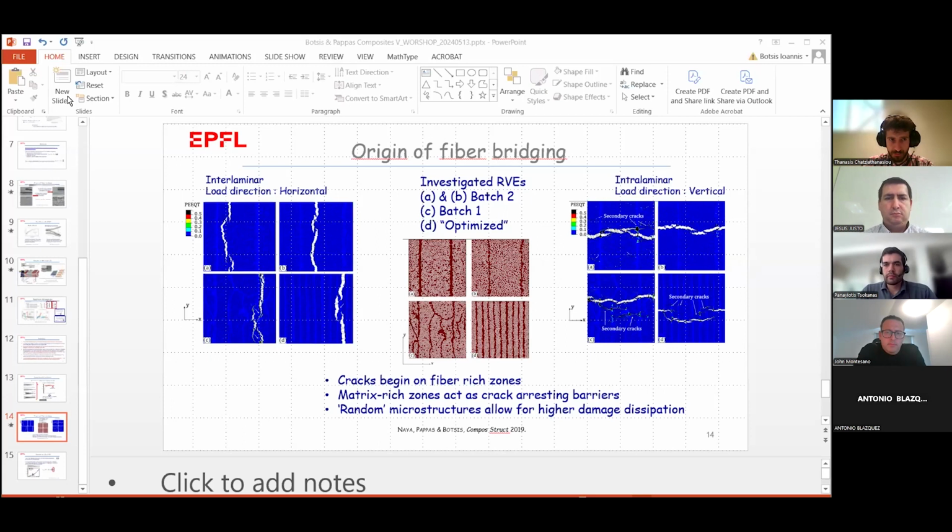At the very beginning, we are talking about delamination involving 10 fibers, 15 fibers, which is nothing. Now, when you obtain bigger delamination values, you notice it in the microstructure. If you are in mode one, the separation between fiber and matrix is like this. If you have mode two, it is like this. And you have mixed mode, is like this. So by simple observation, you confirm that when the delamination crack is very big, you have mixed mode.